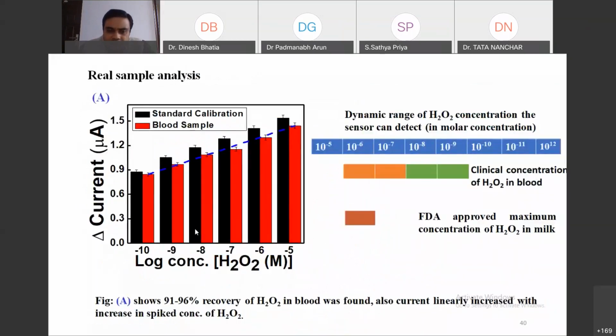And this is the real sample analysis that we have done in blood. In the blood condition, it is behaving more or less the same as the standard condition. And not only in blood, detecting hydrogen peroxide in milk is also possible, because the FDA-approved maximum concentration of hydrogen peroxide in milk is 10 to the minus 6, and our sensor is able to detect from 10 to the minus 5 to 10 to the minus 12. So this is very much important. So this is the comparison. As I said, it has the lowest detection limit reported until 2019.